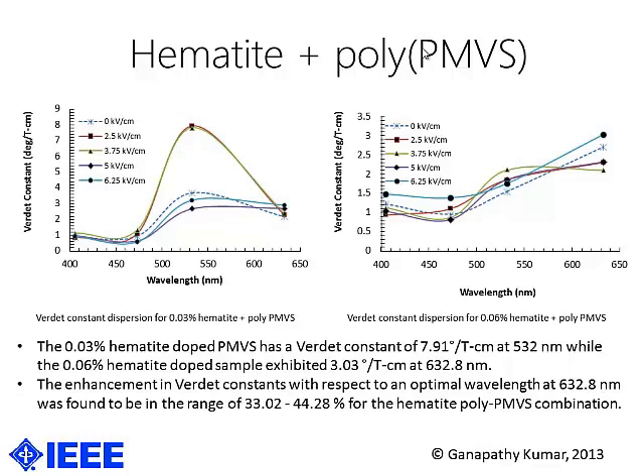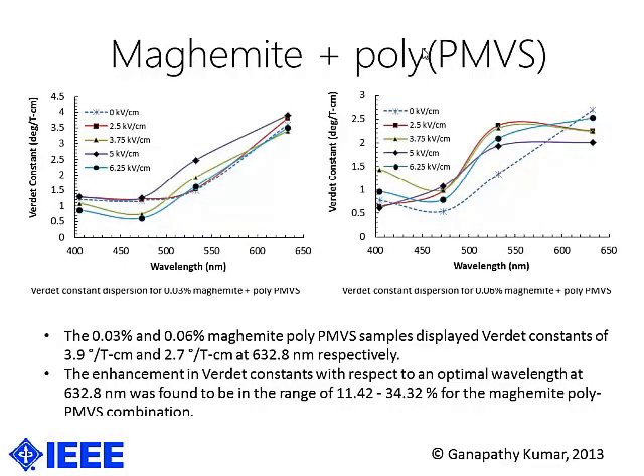The enhancement is basically because of an optimal wavelength at 632.8 nanometers, corresponding to the frequencies that we were measuring at. And the resonant energy for hematite is about 2.2 electron volts, and compared to that, the wavelength at which we could observe a maximum Verdet constant was around 530 nanometers. And when we looked at how much the enhancement was in terms of the Verdet constant, it was about 33 to 44% across all these wavelength frequencies. Similarly, for maghemite, we had Verdet constants at about 4 degrees per Tesla centimeter and about 2.7, and that was at 632.8 nanometers. Now, this one has a resonant energy at about 1.9 electron volts, so we had it closer to the 600 nanometer range.